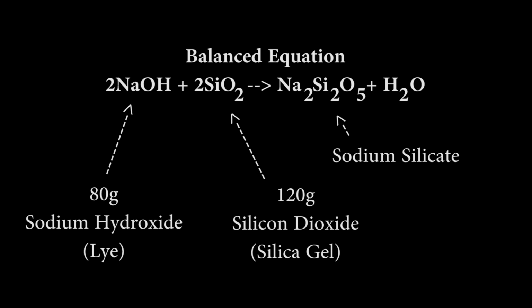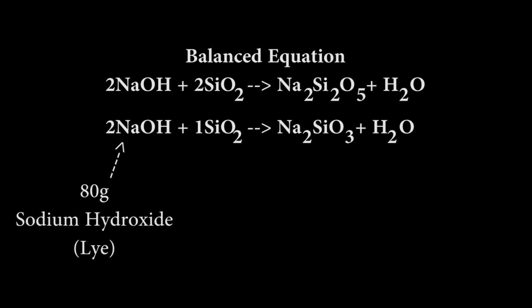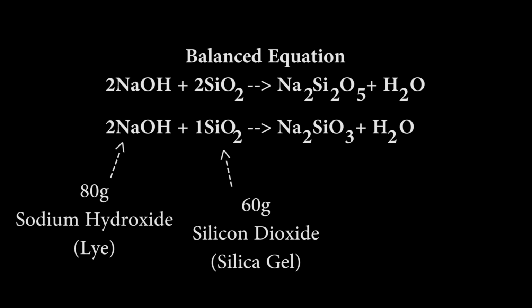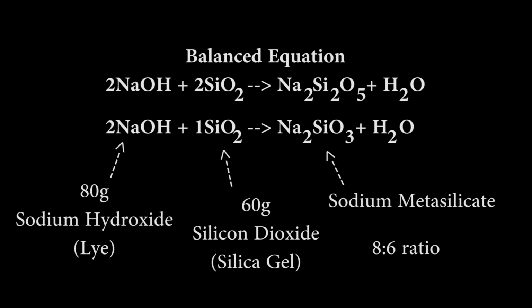It's also generally recommended that for refractory uses or for high temperature uses, a more silica-rich mixture be used, like the one I'm showing you now. But for amateur uses, a sodium-rich mixture will work just fine. I used a 2 mole sodium hydroxide to 1 mole of silicon dioxide ratio for my mixture. I hope I didn't lose anyone in all this. I just wanted to explain where my numbers are coming from.